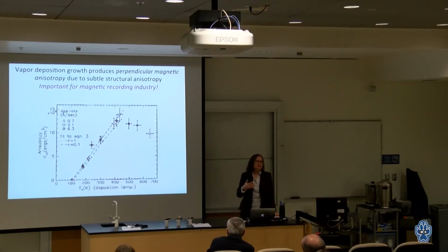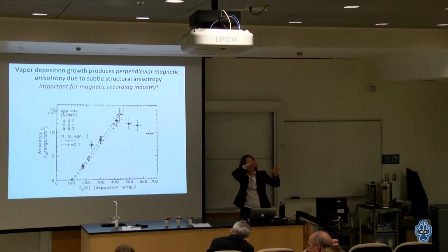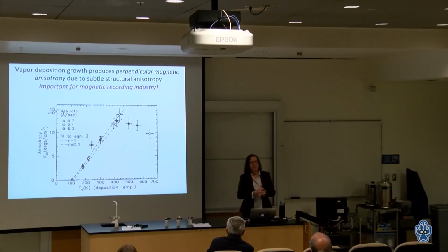There's a way in which at some point you might lose track of the surface. Thicker films tend to get lumpier, and once things start getting lumpier, the angle of the surface is less well defined. But I would hesitate to really say that. We've never grown a millimeter film, we've grown micron films. At some point, the surface may be so rough that the angles are no longer well defined. But I don't know if that would ever happen because it's still, loosely speaking, a surface, and so there's still an out of plane on average.